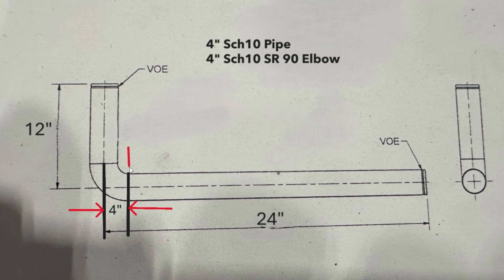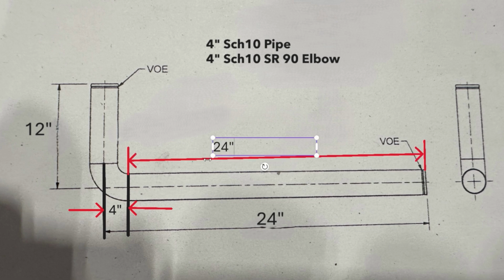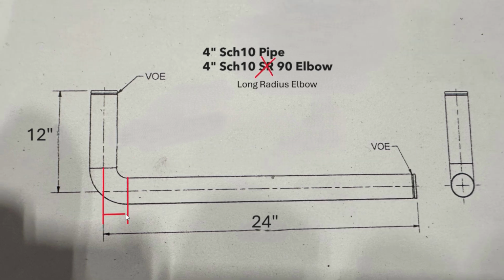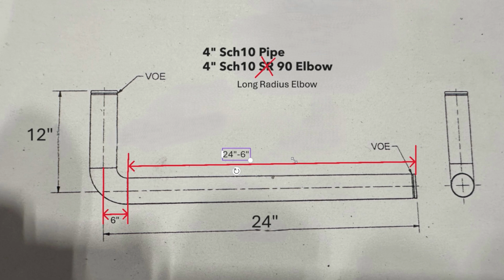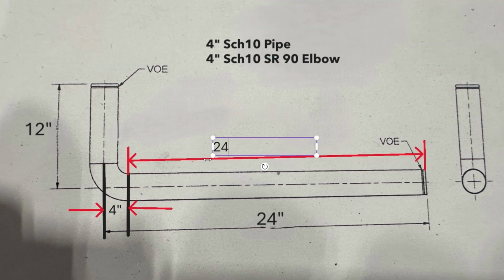So, how long should I cut the pipe? 24 minus 4 is 20. The pipe cut length is 20. If it is a long radius elbow, the elbow center to end is 6 inch. Then, the pipe cut length is 24 minus 6, is 18. Some people may say that I'm wrong because I did not consider shrinkage after welding.